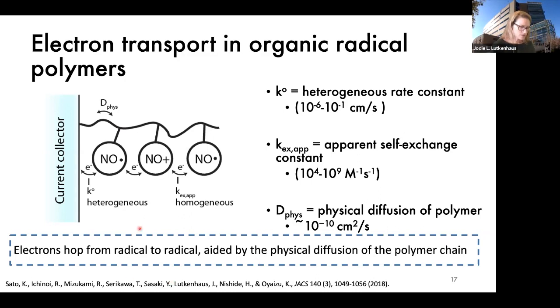transfers. So we consider two methods of transfer. One is electrons exchanging from group to group. We can talk about inter versus intramolecular charge transfer. I'm not sure that that's really clearly defined right now. I've seen people claiming either one, and I'm not sure which one really dominates, honestly. Then once the electron gets close to the current collector, it can hop into the current collector to then transfer charge to the external circuit, and those are represented by the heterogeneous rate constant and the apparent self-exchange constant.